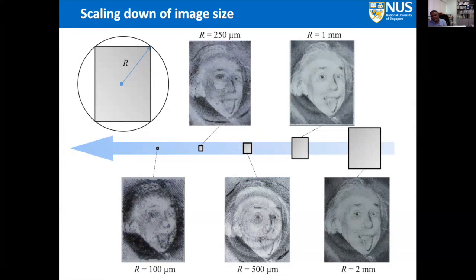The machining time of these images is about 320 minutes for an R of 2 mm, whereas it is 21 minutes for an R of 100 micron. So you can see that there is a considerable decrease in the time when the entire image size is smaller. But you also see that the quality of the image deteriorates, or rather becomes bad, when the size becomes very, very small.